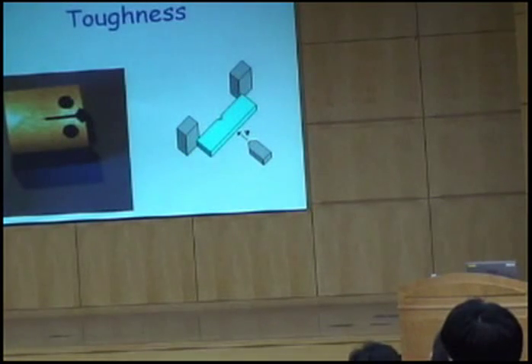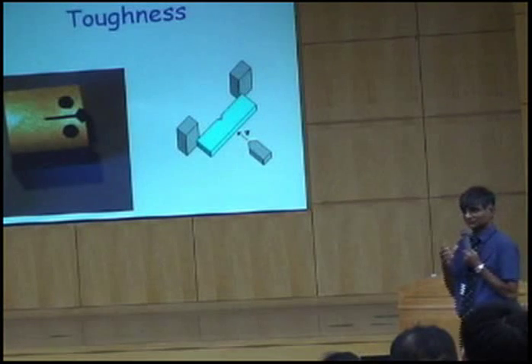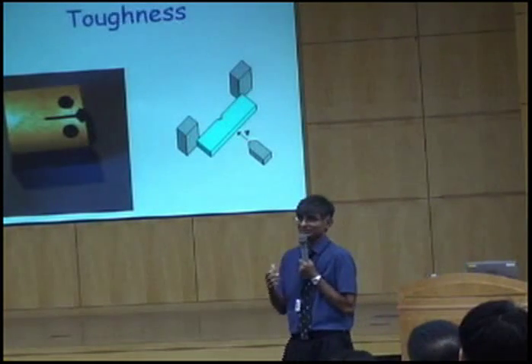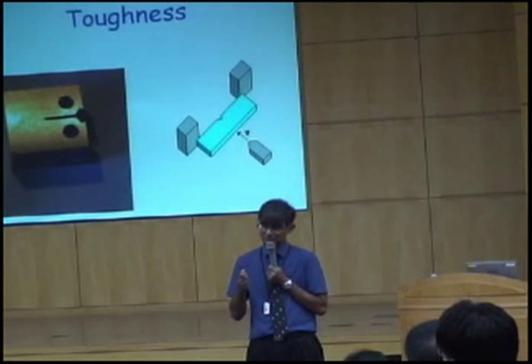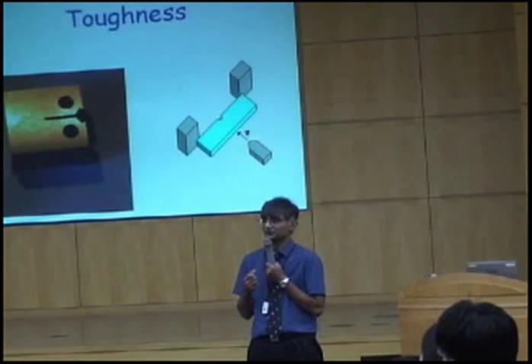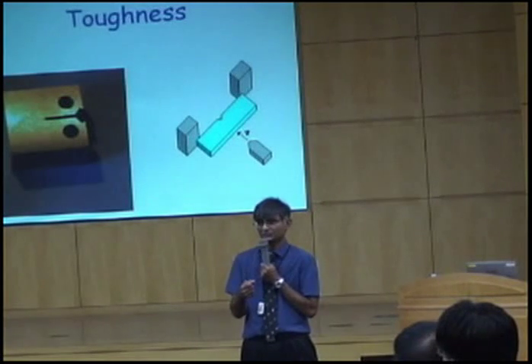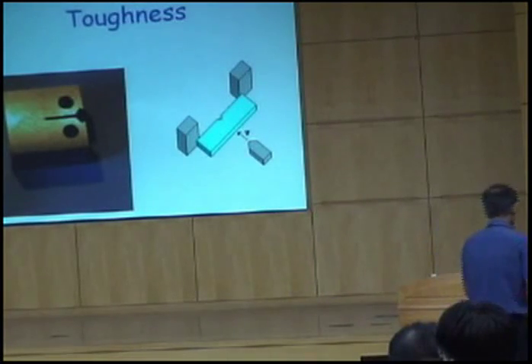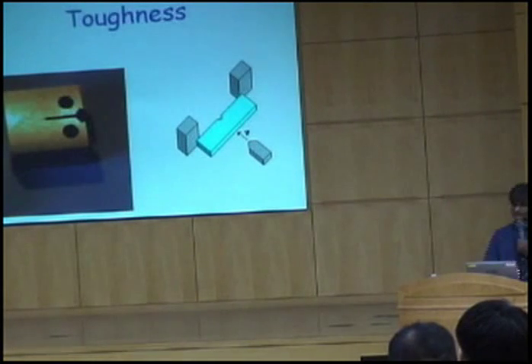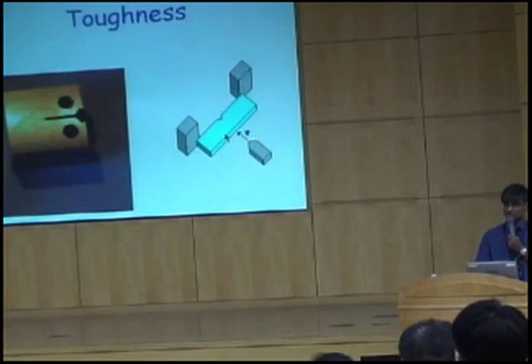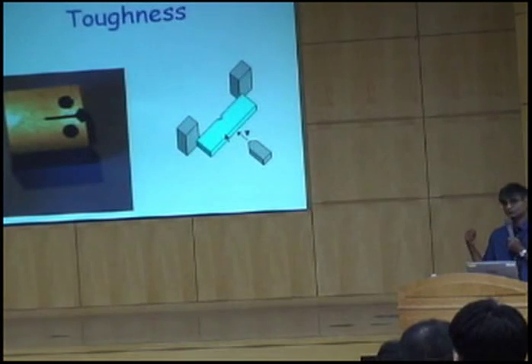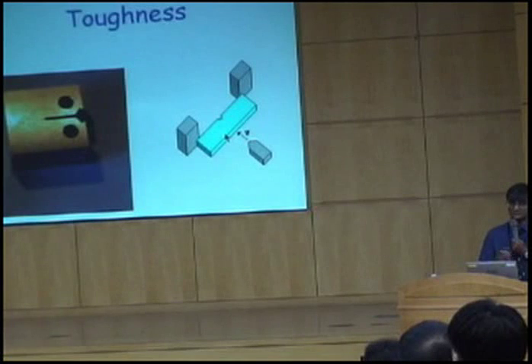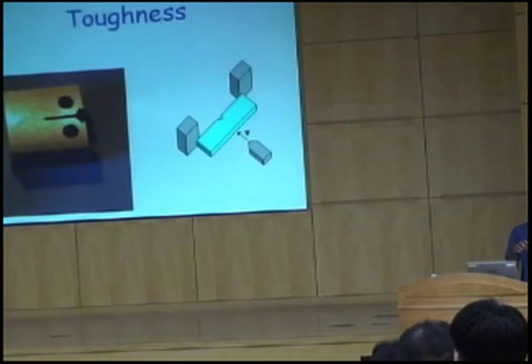Okay, let's now move on to toughness, because anybody can produce a very strong steel. The difficult thing is to produce a steel which is strong and also tough. Toughness is the ability of a material to absorb energy before fracture. It's a very simple idea, and we measure it in several different ways. The most common is the Charpy test. You make a specimen, you hit it very fast, and you measure the absorbed energy. The Charpy test is a very good quality control experiment. You cannot use that number to design a steel structure, but it's a very good quality control test.